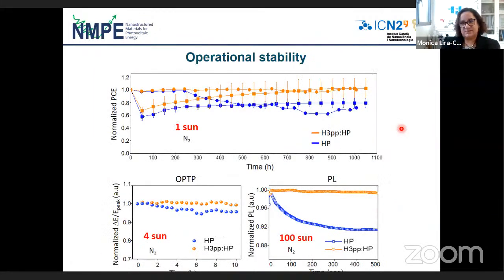What happened later is here, this is the most important part, because we analyzed 1,000 hours under one sun in nitrogen, and you can see the orange curves correspond to our solar cells with the additive, and the blue curves correspond to the solar cells without the additive. You can see we have circles and squares - it means we have two different types of halide perovskite.